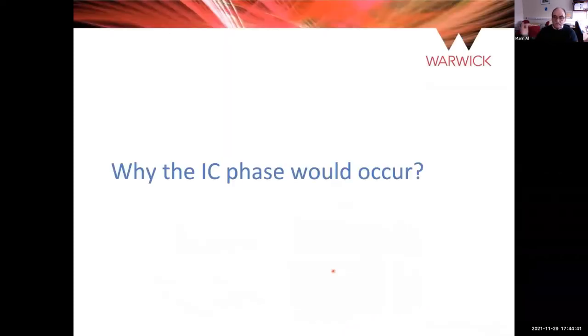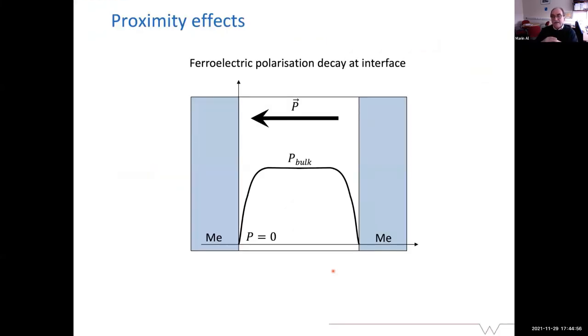So why would this phase occur? That's the main question. Why is this very particular phase going to occur in strontium ruthenate on strontium titanate? And if we think a little bit more, we have charge polarization on that. The strong polarization in the ferroelectric layer, and a relatively lousy, or not lousy, metal, which is not really a metal. So it's not a classical metal. Strontium ruthenate has a metal behavior, but does not have a metal bond.